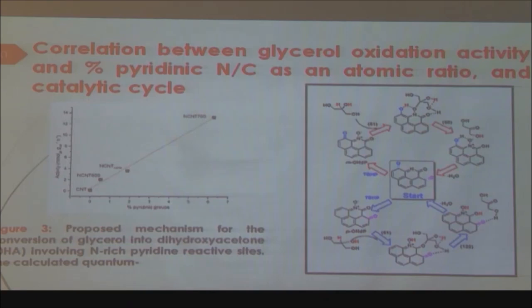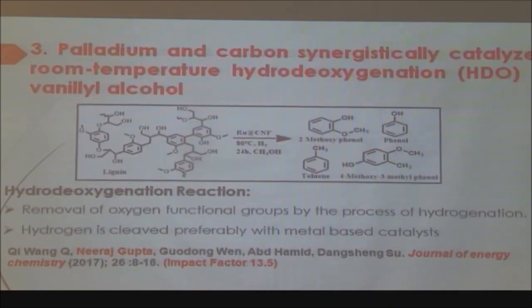Again, the catalyst is good if you can reuse it. So we were able to reuse our catalyst for 8 cycles, where almost the same catalytic activity was obtained. So 36% conversion was there everywhere. This catalyst, nitrogen containing CNT, was found to be very good for oxidizing plant derived glycerol, where it was able to selectively make dihydroxyacetone out of three possible products. So the selectivity of this catalyst was also very good. So it has a very good use in the biomass industry.